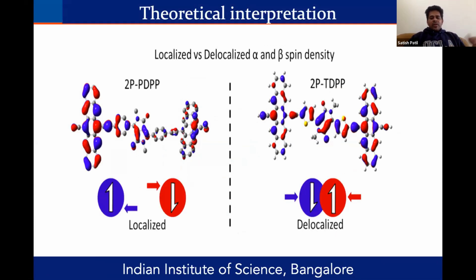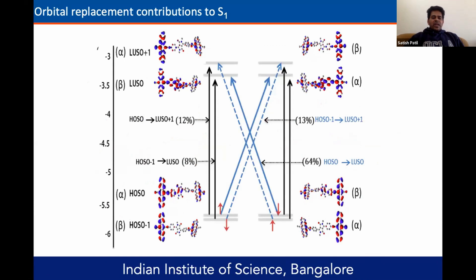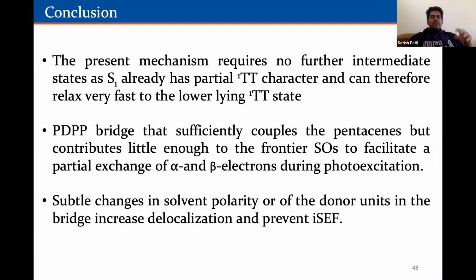Then we did a lot of computational studies, and we came up with the idea of how the spin density localization on the pentacene dimer plays an important role, when you have localized spin density and delocalized spin density. So these are the more detailed computational studies. What is happening here is that the present mechanism, whatever we propose, does not essentially require this; the singlet state already has a partial TT character. That's one of the major outcomes. And the bridge plays a very important role in how it contributes to facilitating the exchange of alpha and beta electrons, and the solvent polarity. I did not touch upon it, but indeed it plays an important role.